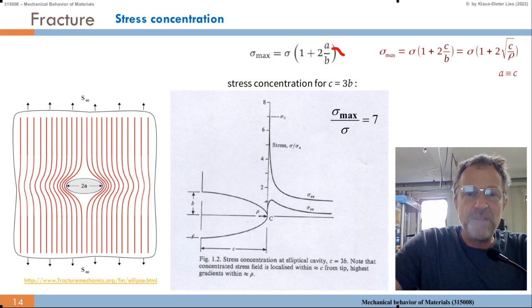If we have the ellipse, we have here the maximum curvature, which is the minimum curvature radius there. If we apply the stress in the y direction, then sigma critical, or sigma max, becomes 7 - the 6 plus 1. 6 times through the stress concentration, and 1 times through the applied stress. This is the sigma yy.